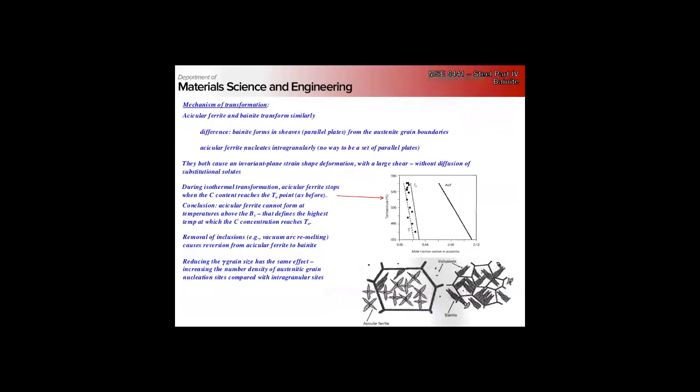Earlier you said you were going to point out the difference between upper and lower Bainite. Is that purely the dispersion of cementite inside the Bainite? For the purposes of the class and the exam, yes. They just have slightly different morphology: at upper Bainite, you're at temperatures where you have faster diffusion of the carbon, and so all of the carbides form outside, between the subunits, whereas at lower Bainite they form inside.